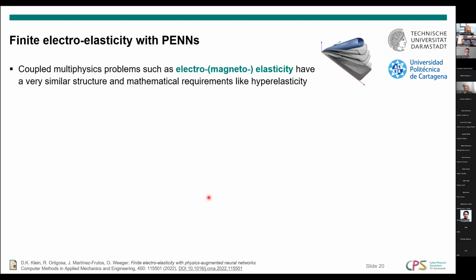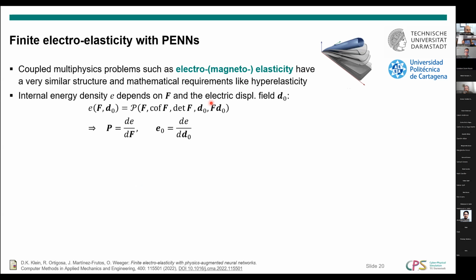Okay, then the last extension of this model that I want to show is going to multiphysics, in this case to electroelasticity. So for instance, for modeling electroactive polymers, you have this interaction between electric and mechanical behavior. And luckily, the mathematical structure of these problems is very similar to the case of hyperelasticity. So basically here, in order to model the material behavior, we need to find the so-called internal energy density function E, which now needs to be a convex function in terms of the mechanical deformation gradient, the cofactor, and the determinant, as well as the electric displacement field and some combination or rotation of the electric displacement field.